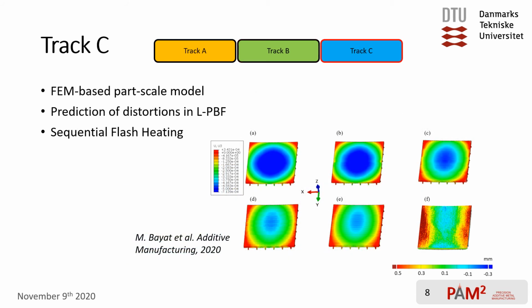And in the final investigation track, I developed a part-scale and FEM-based thermomechanical model for the prediction of distortions in LPBF, where I used the sequential flash heating technique, and we found that if we use a sufficiently fine stripe size in the sequential flash heating technique, we can have a very good agreement between the numerical predictions of distortions and the distortions found by experimental methods.